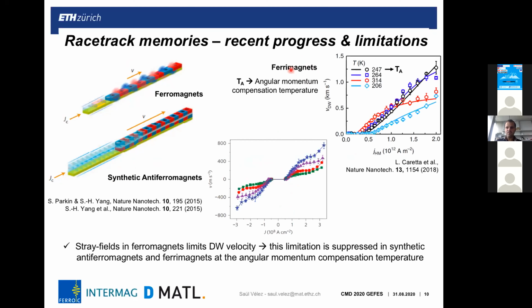When you move away from the angular momentum compensation temperature, the system becomes more ferromagnetic, and then the domain wall velocity is limited by the fact that you have stray fields. But when you go to the angular momentum compensation, then you get a higher velocity in the system, and it was even demonstrated that you can move domain walls above 1 kilometer per second. But another limitation is the fact that you have pinning, you have defects in the system, and this prevents you from driving domain walls at moderate charge currents.